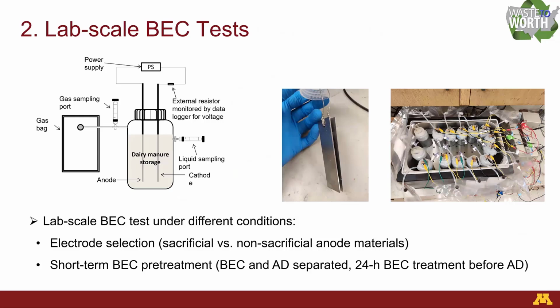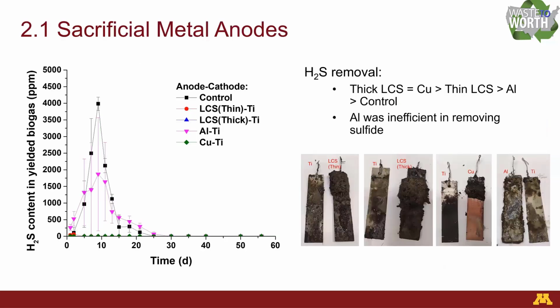This is a schematic of the system. So we tested 2 batch tests. First of all, that's electrode selection. We want to compare the sacrificial and non-sacrificial anode materials to see the effectiveness of hydrogen sulfide removal and also their effect on the following biogas production. The second one is we want to see if we can separate the BEC system and the anaerobic digestion, so we can directly apply it in a short term and reduce the volume of the reactor. So this is the first